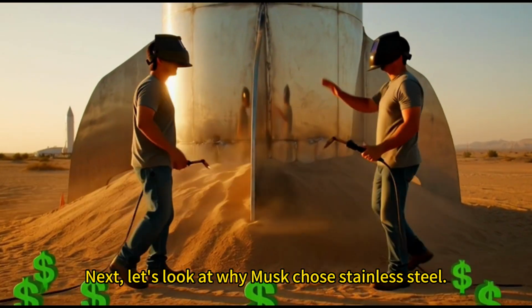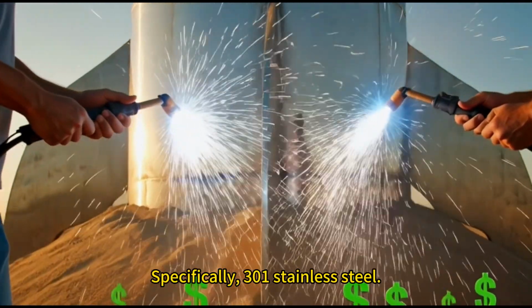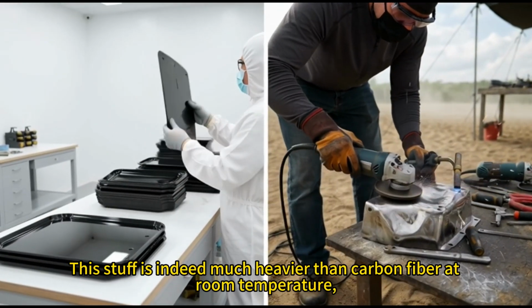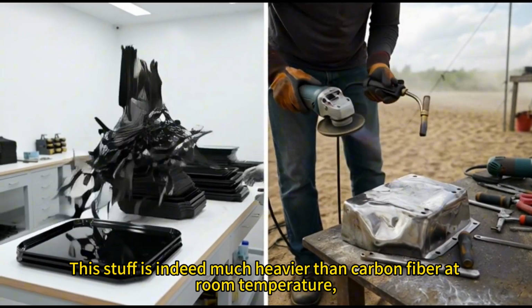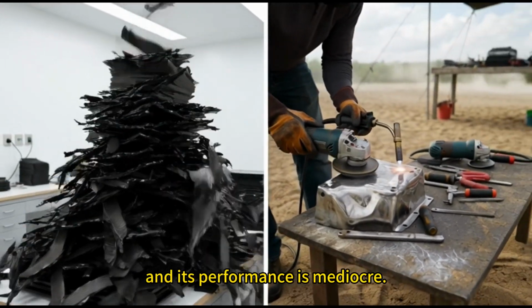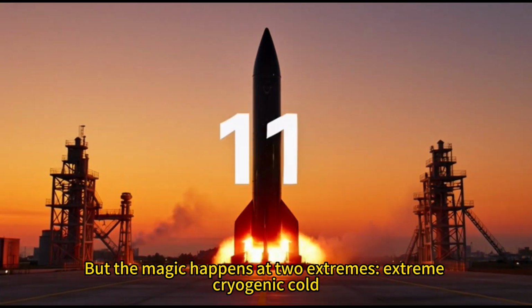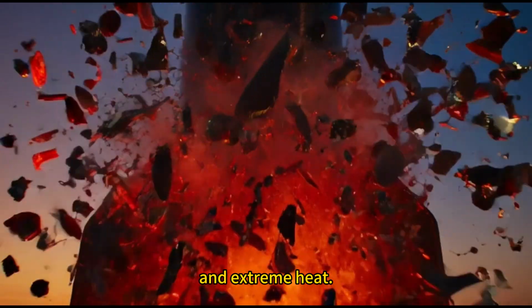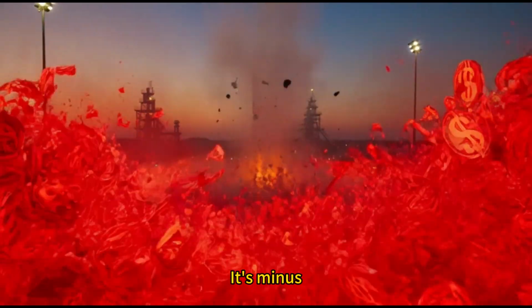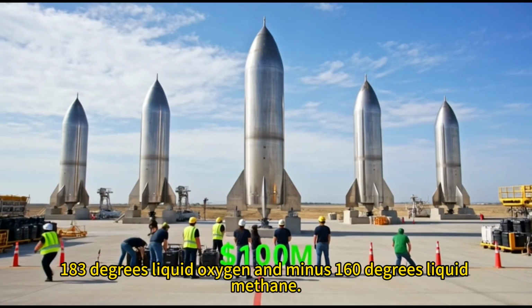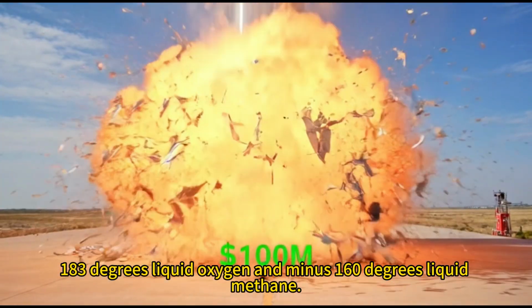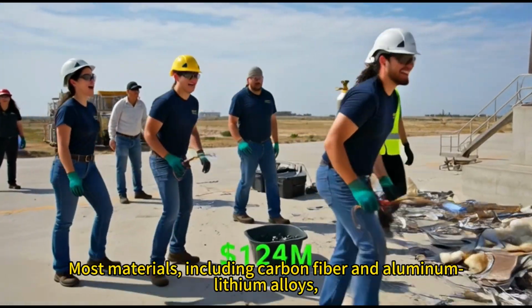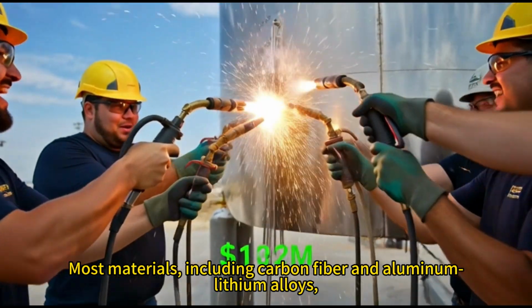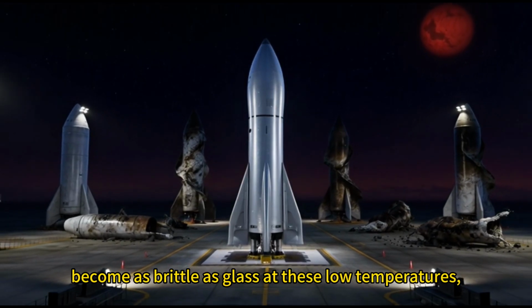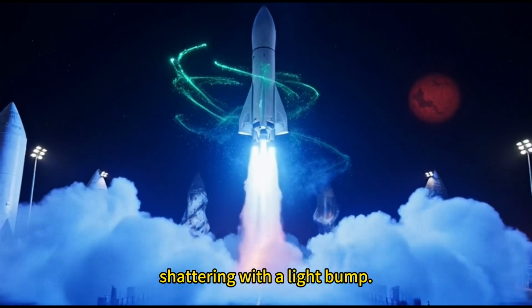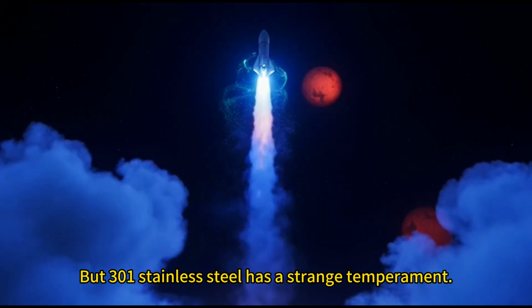Next, let's look at why Musk chose stainless steel. Specifically, 301 stainless steel. This stuff is indeed much heavier than carbon fiber at room temperature, and its performance is mediocre. But the magic happens at two extremes: extreme cryogenic cold and extreme heat. What's inside the rocket's belly? It's minus 183 degrees liquid oxygen and minus 160 degrees liquid methane. Most materials, including carbon fiber and aluminum lithium alloys, become as brittle as glass at these low temperatures, shattering with a light bump. But 301 stainless steel has a strange temperament.